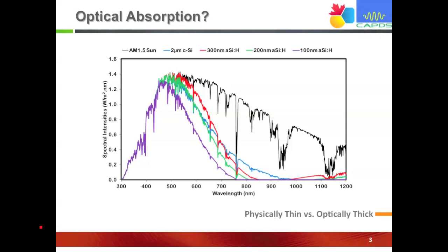As we see, 200 nanometer and 300 nanometer amorphous silicon look like they have the same absorption. Also, we have lots of space for improving the device in the IR part by applying some sort of advanced light trapping technique or other things. We could make use of this part of the high wavelength spectrum that doesn't provide any contribution to the optical absorption. This shows us that specifically 200 nanometer layers are very attractive for this application.